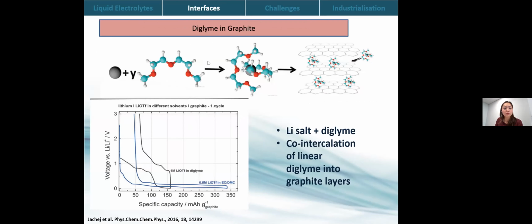And so now I move on to diglyme and graphite. So this is a paper that showed that with the lithium salt and the diglyme, there is a co-intercalation of the linear diglyme into the graphite layers. So when we look at the voltage versus capacity profile of the lithium salt in diglyme and the lithium salt in EC/DMC, we see that in EC/DMC, we have a good specific capacity. And when the solvent is changed to diglyme, it seems like there's a huge hysteresis, and also the capacity is limited here. And this is due to the co-intercalation of the linear diglyme into graphite layers.